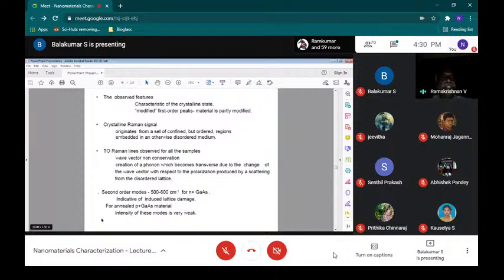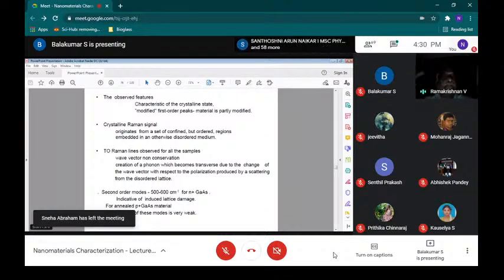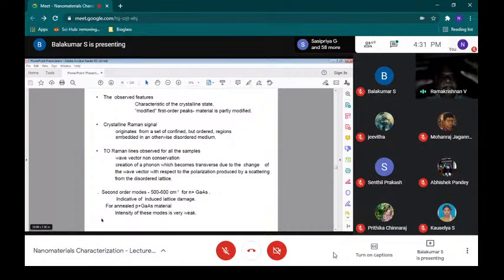Okay. So the observed features tell that it is characteristic of the crystalline, because you have seen the LO mode and the TO mode. Both peaks are there. So you have modified first order peaks, because the forbidden mode is also coming. That means the material is partially modified. So the Raman signal tells that the signal has come from a set of confined but ordered regions, otherwise embedded in a disordered region.